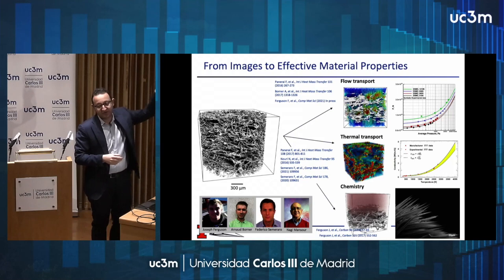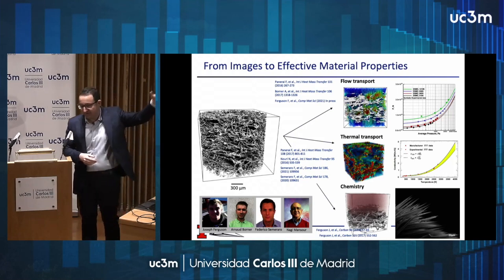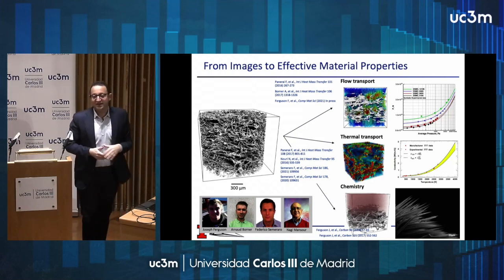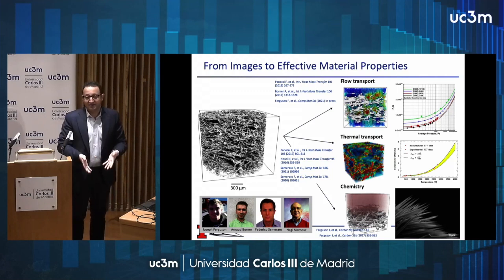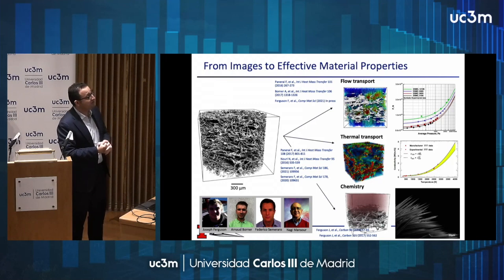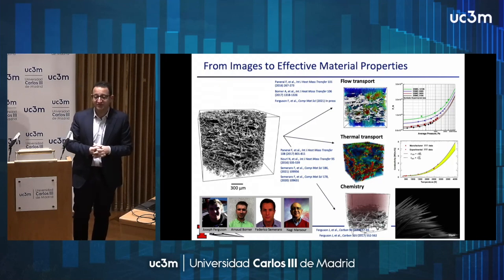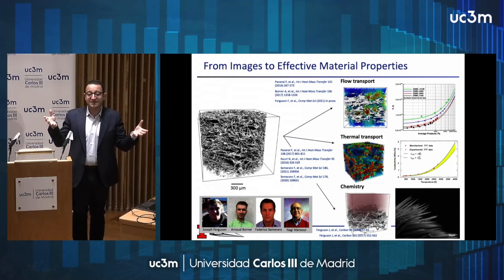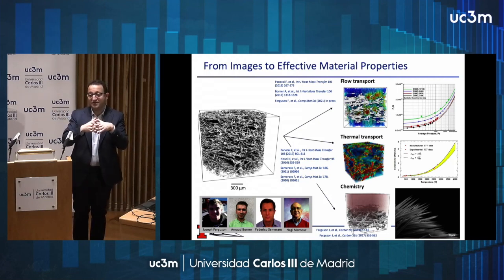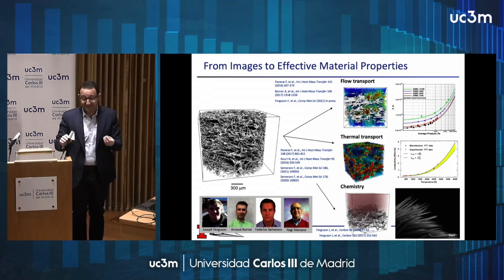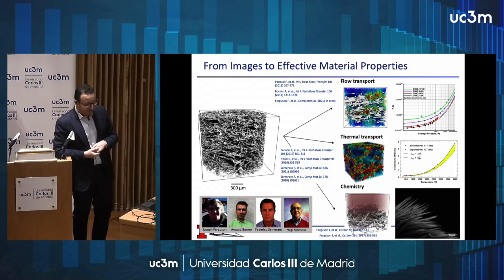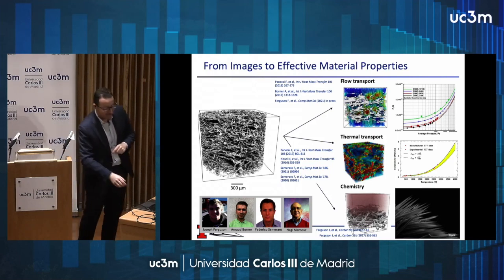So you can use it to simulate flow transport, to determine material permeability or tortuosity, and look at how the flow is transported through the pores. You can use it for thermal transport. The resulting thermal conductivity of these composites is given by the way the fibers are organized, the thermal conductivity of the fibers, plus the thermal conductivity of the gas contained in between the fibers. And then you can use it to resolve chemistry.